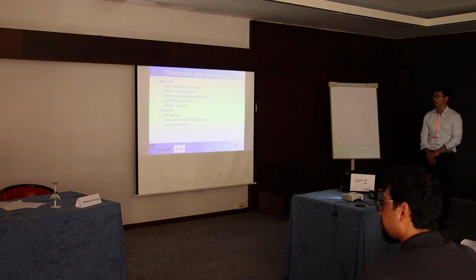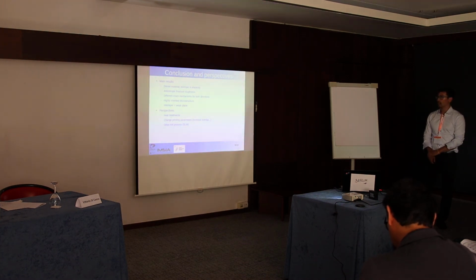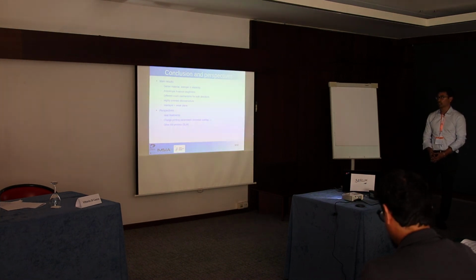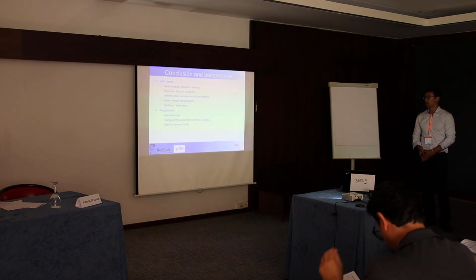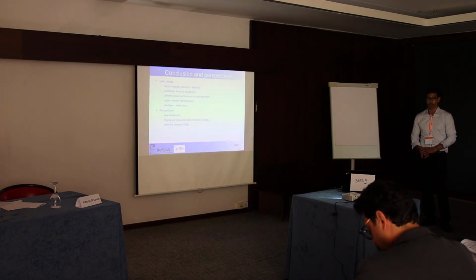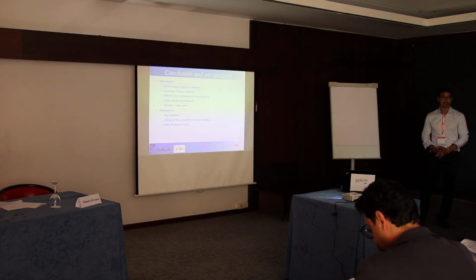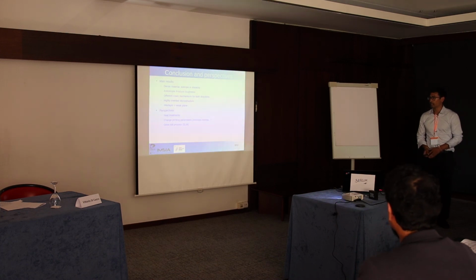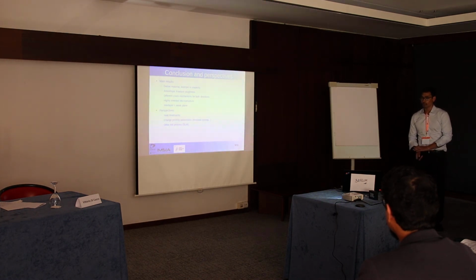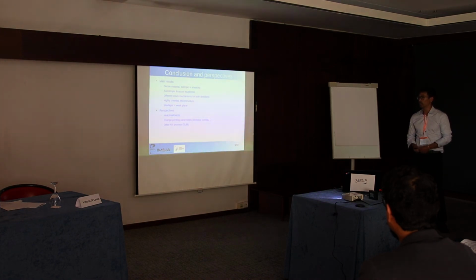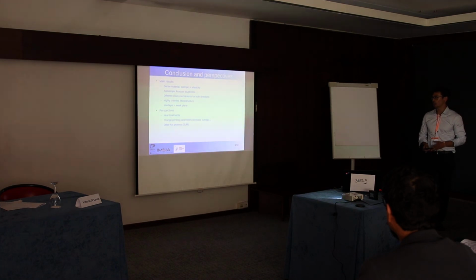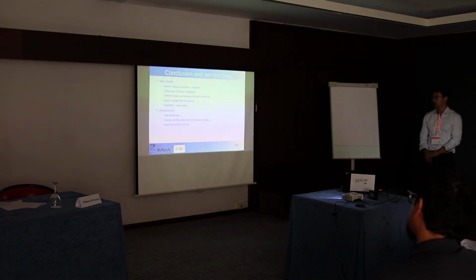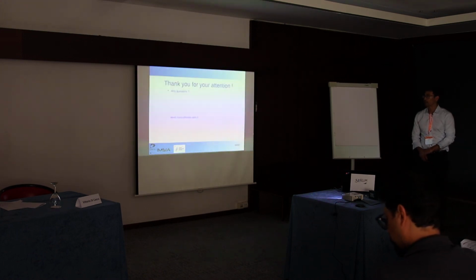So to conclude on this presentation, we have seen that we were able to print a dense material which appears to be isotropic for the elastic properties. However, we have seen that the printing direction has a very important influence on the growth of cracks. This appears to be explained by a very highly oriented microstructure and essentially weak planes in the interlayers which can guide the crack. So some perspectives to this work are to try and modify both the phase composition as well as the general structure of the material, for instance by performing some heat treatments or changing some parameters, or even trying other fabrication processes. Thank you for your attention.